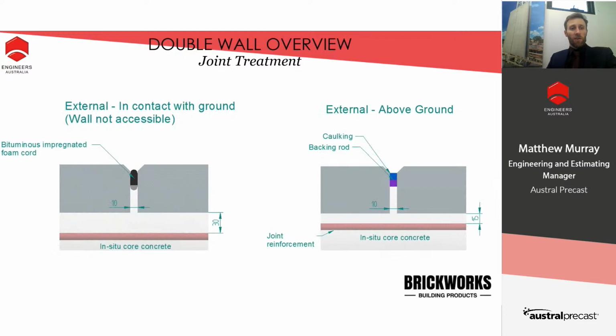Joint treatment. So double wall can be treated typically the same as you would traditional precast. So above ground, we will be using a backing rod for the panel joint to stop any slurry coming out of the panel during core filling, and that can then be completed either before or after core filling. A caulking can be applied to that for a traditional precast finish.